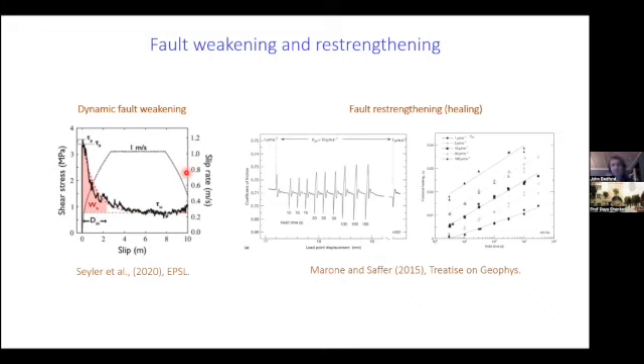And fault healing has been studied for quite a long time in the laboratory, but typically it's studied at very low sliding velocities, on the micron per second range. And the way fault healing is studied in these studies is to perform experiments which are called slide hold slide experiments, whereby you take an experimental fault, you shear it a little bit, and then you stop the shearing and hold the fault in stationary contact for a predetermined amount of time, and then you re-shear your fault, and you look at how the fault strength evolves as you re-shear. And you can see some examples of these slide hold slide events here, where the hold time is indicated as the number below, but the peak strength achieved after the initiation of sliding, after the hold, increases the longer it was held in stationary contact.